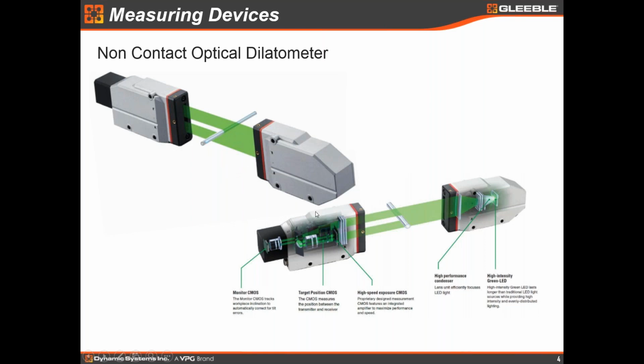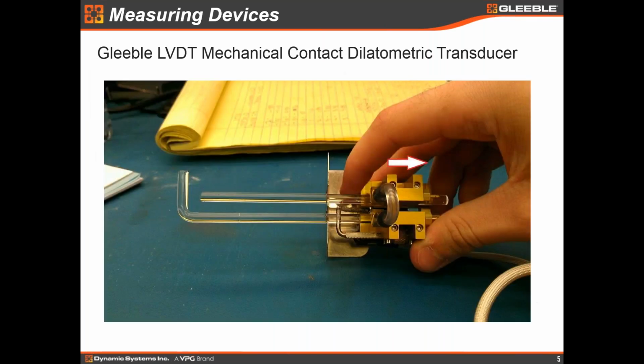I won't go into a lot of information on the optical dilatometer. It's a very nice device. It doesn't require a lot of setup. Once you have it attached to the Gleeble vacuum tank, you don't have to clip on and off the extensometer, so it's got some benefits. It does have some high temperature limitations, although the newest model is quite good. It has enough high intensity light to measure the dilation of a sample even at quite high temperatures when the sample may be fluorescing quite strongly as well.